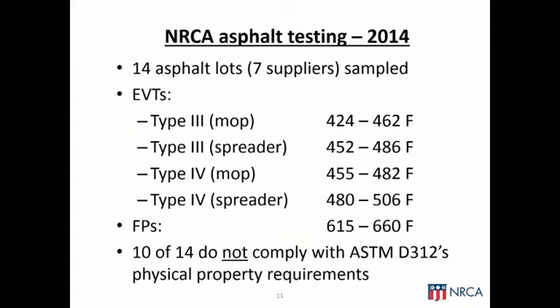At the same time all this is going on, I want to point out that the ASTM standard for asphalt still says a minimum flash point for asphalt should be 500 degrees. And that's what we are seeing on most asphalt suppliers' product packaging, markings, things along that line. So we actually have some asphalts that have EVTs higher than their labeled flash point temperature, which is just totally counterproductive to, well, A, common sense, and then B, good roofing practice.